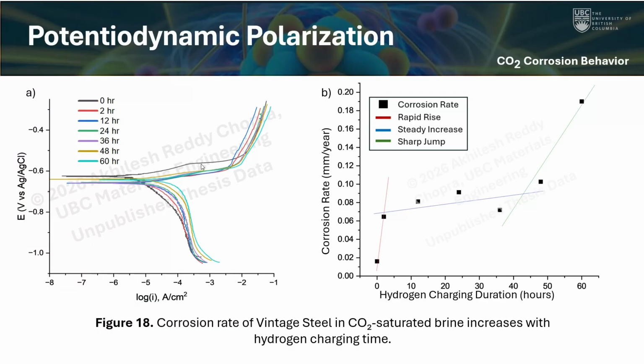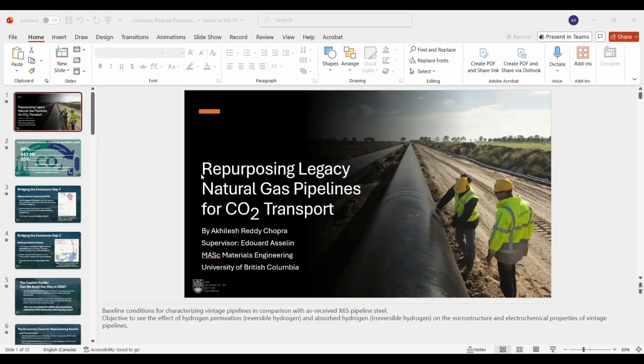And so that also tells me that it's not just a surface phenomenon, but the hydrogen itself. If hydrogen atoms are within the steel, the iron lattice, those areas become high strained regions compared to the base lattice. Because of that highly strained area, steel may be more willing to give up an electron and oxidize.